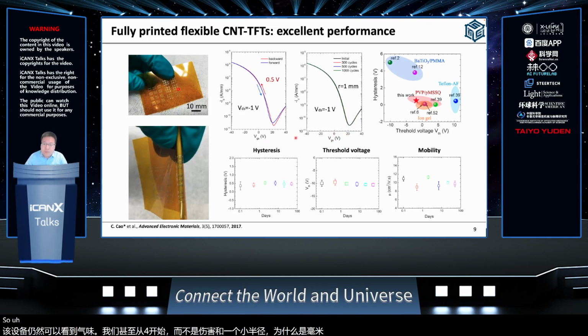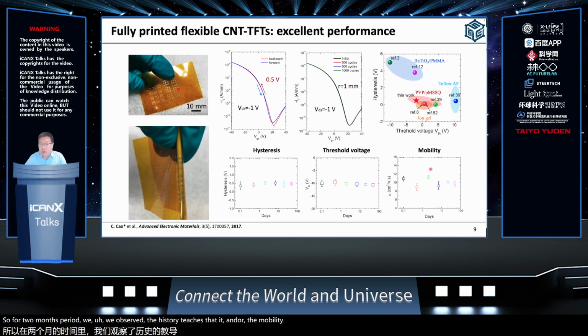Compared to other dielectrics in the literature, our printed dielectrics give a very attractive performance, with a small hysteresis and a small threshold voltage. Over a 2 month period, we observed that the hysteresis, the threshold voltage, and the mobility of the device can stay at the same level. That means the printed device can be used for the long term without any encapsulation.